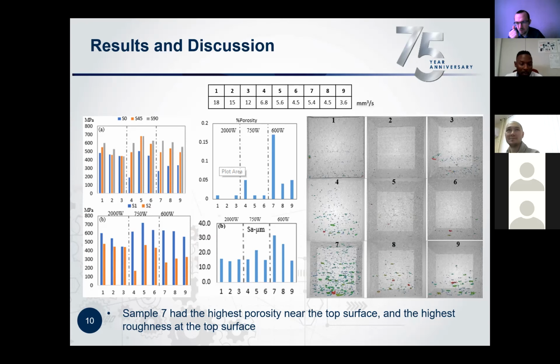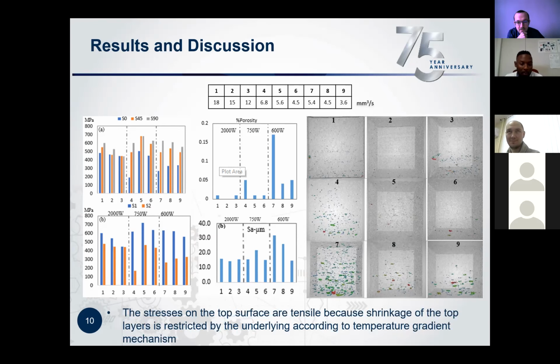And only one small question is: have you cut your samples after these investigations? So, have you looked at the real porosity? Yes, we have done that, but this is not part of these results because micro-CT, when you compare to image analysis by optical microscope, micro-CT is more accurate because you're looking at the entire sample. So when you have this data, there's really no need to go and cut it and look at the porosity. But we have done it in any case to characterize the microstructure.